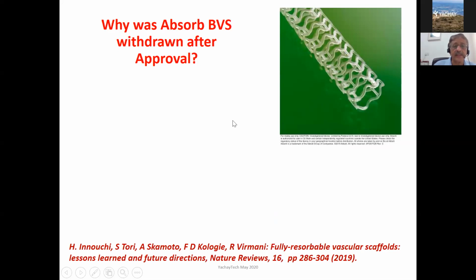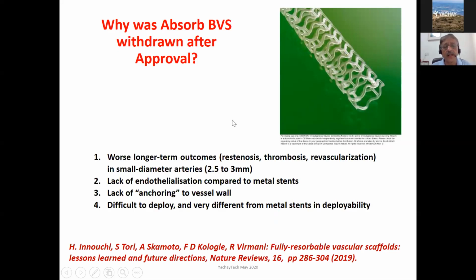Okay, so the reasons that led to its withdrawal had to do with worse, longer-term outcomes: restenosis, thrombosis, revascularization as it's called, which is re-intervention in small diameter arteries compared to bare metal stents. It was also not endothelialized as much compared to, again, bare metal stents, which is a problem with clotting. So the thrombosis happens because of the lack of endothelialization.